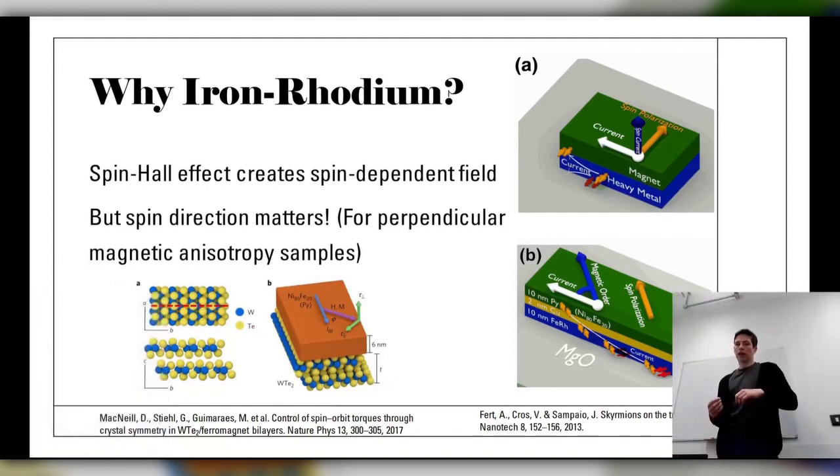Fortunately, this effect not only exists in transition metals, but it also exists in their compounds. And it turns out that when you have lower symmetry compounds, you can modify the direction of spin polarization so that it's no longer perfectly perpendicular to the direction of charge current and the direction of spin injected current. This proves much more useful for manipulating Skyrmions in thin films.